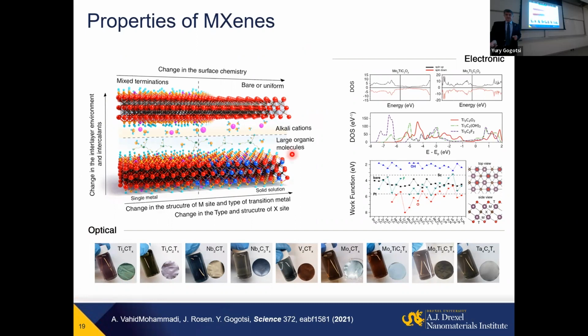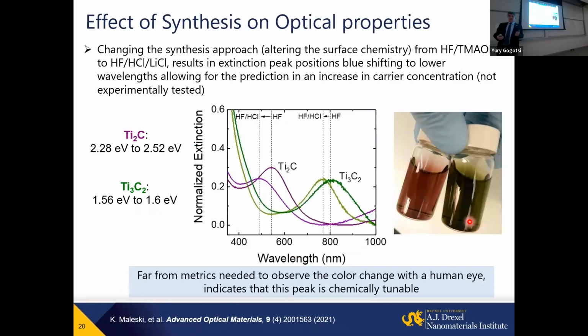And you look at the effect of surface termination now. If you have OH, you get a work function of about 2. You heat it up, break hydroxyl groups to oxygen, and the work function goes to 6. So for optoelectronic applications, solar cells and others, you can see how in an ETL, for example, you can tune the work function to match the work function of, say, the semiconductor you use next to it. So tunability is important. And of course, it can also be controlled by synthesis. You can see, for example, that the transverse plasmons of titanium-2C and titanium-3C2 are different. That's why they have these different colors. But depending on how you synthesize this, what the surface termination is, it also shifts chemically.